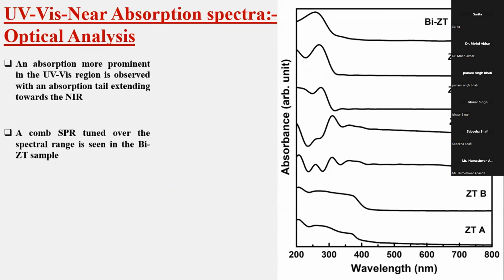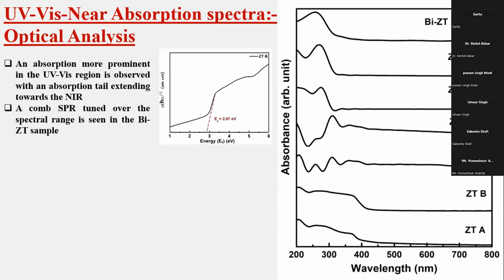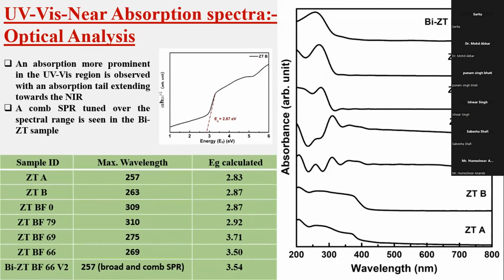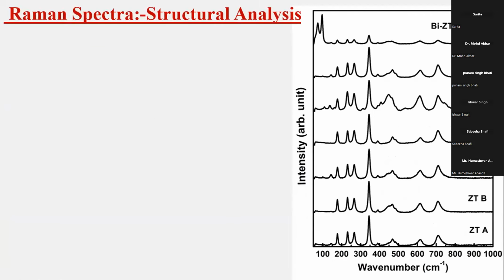So moving to the UV optical spectra, we are giving an optical spectra which is extending a tail up to the NIR region. A combined SPR tuning is seen for the finalized sample with bismuth. So you can cover the entire region. These are the maximum wavelengths we observed for the absorption, and the energy band gap calculated. The final one, the BiZTO optimized film, where the particular energy gap is calculated and the wavelength corresponds to the SPR. This is a Raman spectra, which is for the structural analysis.